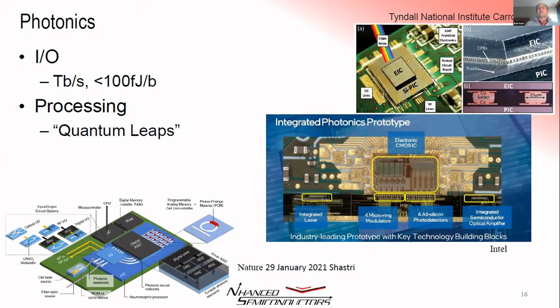But at the same time, silicon photonics, they're very large structures. They're done in much simpler processes. And these are, in this case, solder bumped together. But if you bonded these with hybrid bonding, you can reduce the power consumption by 20 or 30% just simply by removing that interface and doing it with a hybrid interconnect. This goes from being perhaps 150 or even 200 femtofarads. This interface becomes as small as single-digit femtofarads, and in most cases, less than 20 femtofarads.